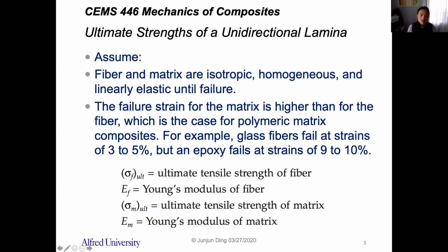Okay, so now we assume the fiber and matrix are all isotropic and homogeneous and linearly elastic until failure. So that's the assumption for this model. And the failure strain for the matrix is higher than the fiber, which is the case for most of the polymer matrix composites, right? For example, for the glass fiber reinforced epoxy composite, the glass fiber fails at a strain around 3 to 5%, while the matrix material epoxy fails at a strain around 9 to 10%, right? So usually for the polymer matrix composite, the maximum strain for the fiber is smaller than the maximum strain for the matrix.